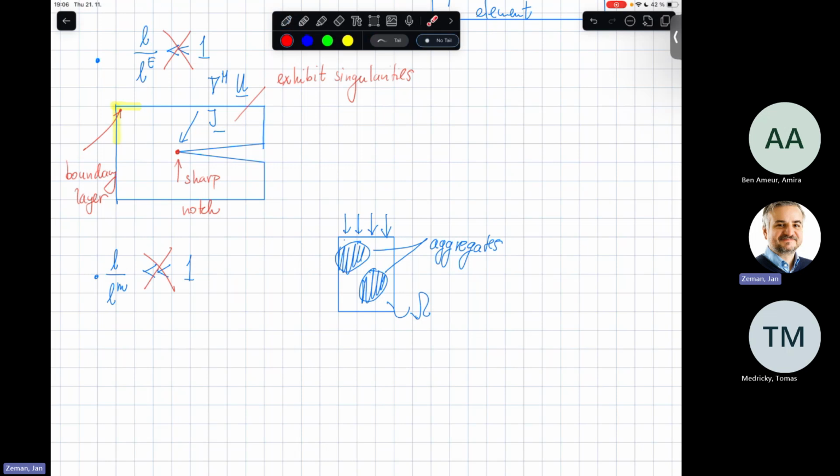So in this particular case, the behavior is dominated very much by what happens in the close vicinity of the boundary. So if you have some hard particle, for instance, adjacent to the boundary, this is different than if you have it farther. So if you just shift your microstructure, its behavior will change, and hence the apparent properties are not really homogeneous.